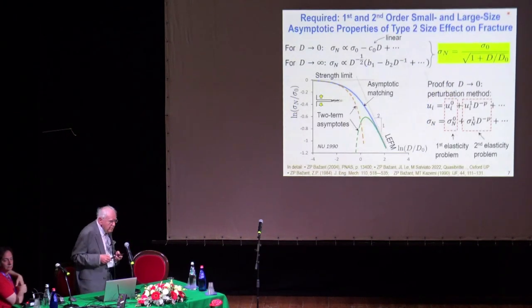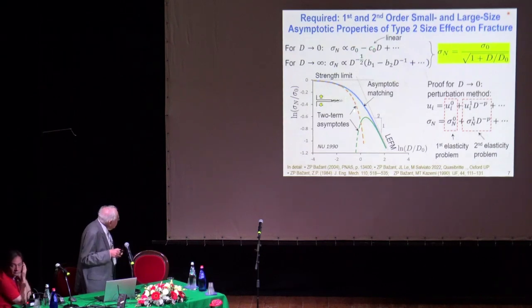However, it can be done more systematically, which came a few years later. We take linear elastic fracture mechanics and perturb it, obtaining an asymptotic expansion in size, with negative exponents. This is the expansion for size infinity. And this expansion, if you take two terms, has this green curve. We can also do asymptotic expansion for small size. So this is deviation from strength theory, or from elasticity, in the simplest case. And by perturbation method, you obtain, again, an expansion of two terms. They lead to a sequence of elasticity problems, which have unique solution. You get another expansion. And this is the dashed brown curve.